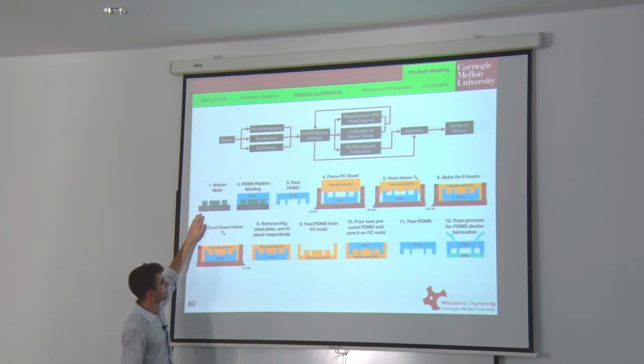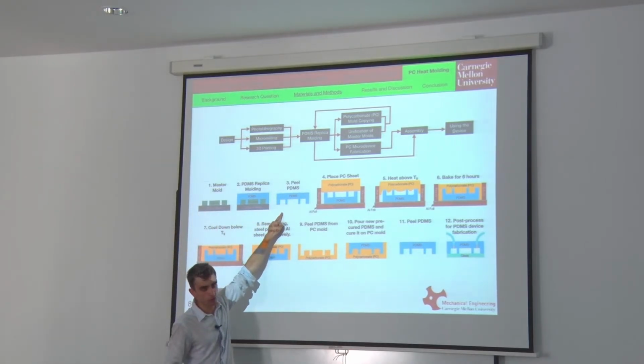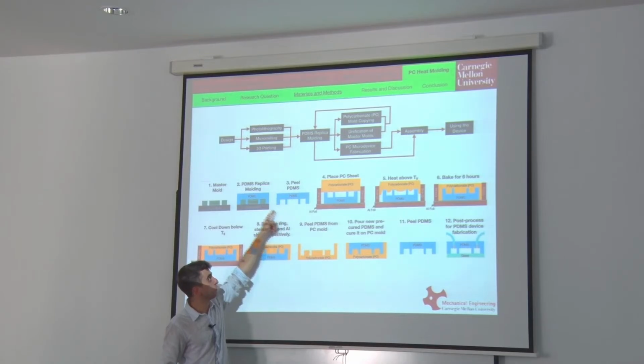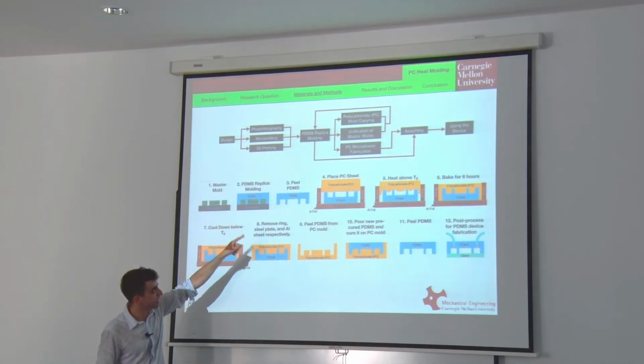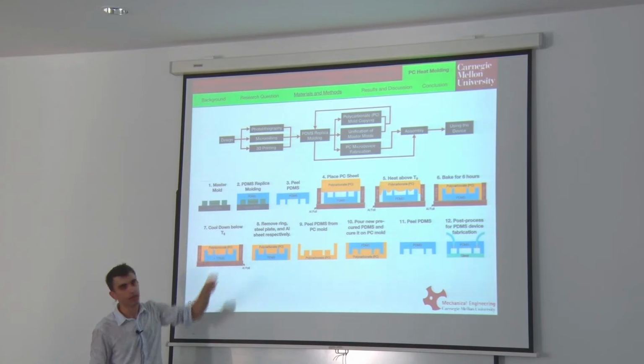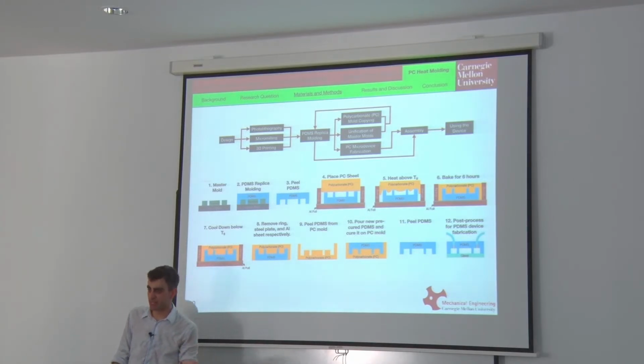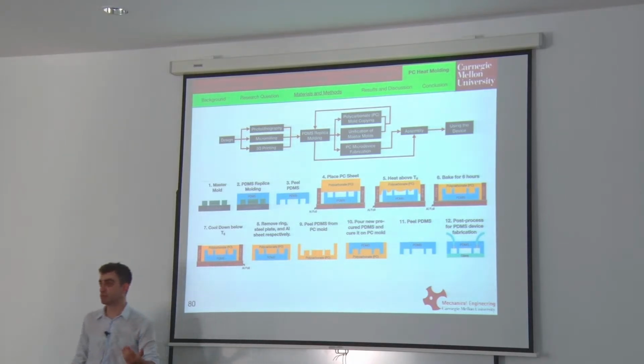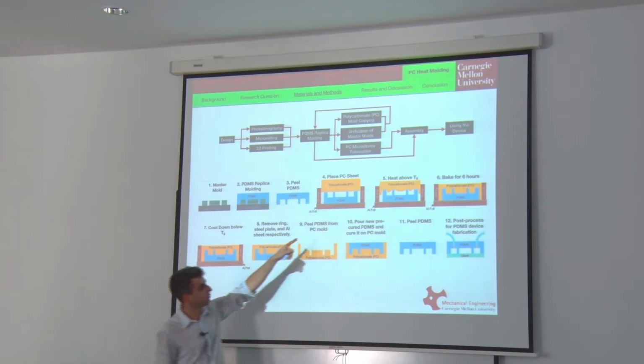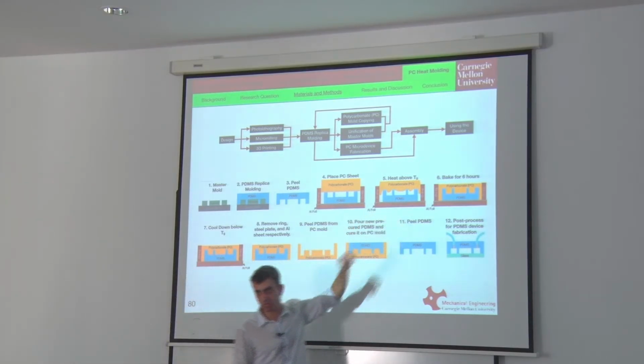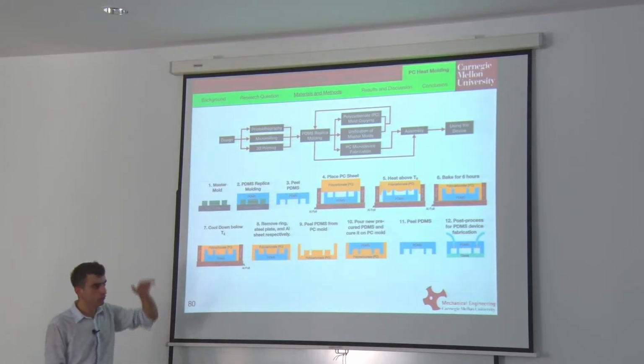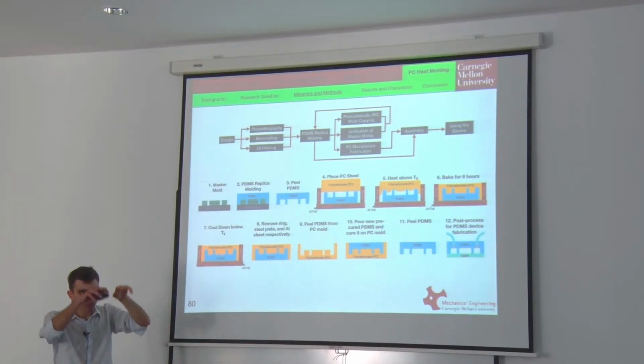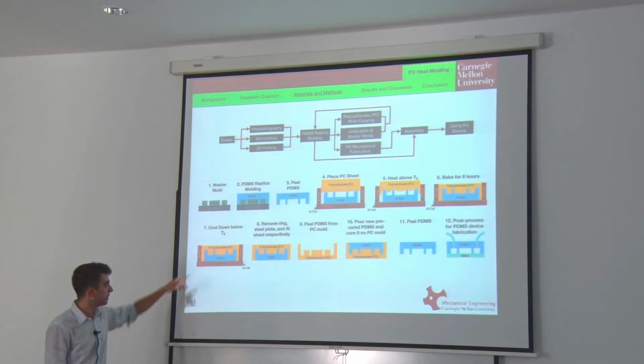So you basically get the same mold. You make a microfluidic channel, PDMS, out of this mold, and then you use this channel and you put a polycarbonate sheet on it. Since polycarbonate is a thermoplastic material, if you heat it up beyond the glass transition temperature, it melts. It melts and covers this microtopology on top of the PDMS functional surface. And if you bake it for enough time, it completely covers this microsurface. And then if you cool it down, it solidifies again.